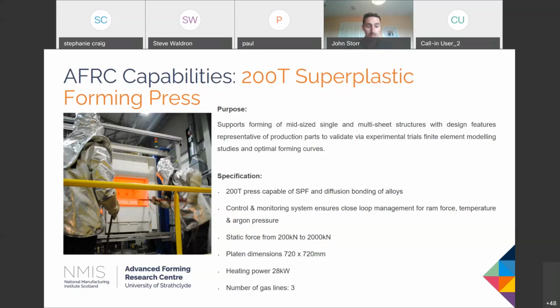And this was installed in 2011. It has a platen size around 720 by 720 millimeters, and it's used typically to prove out process cycles, to look at new material implementation, and to look at different material structures and different geometries that we want to investigate with different pressure cycles before we perhaps move on to then apply those to the larger press that we have. So Steph, if you want to go to the next slide.